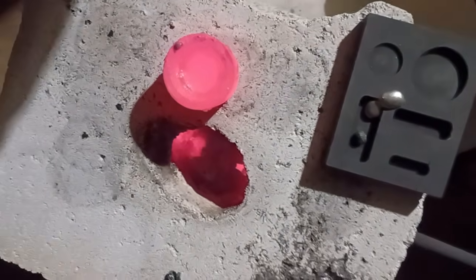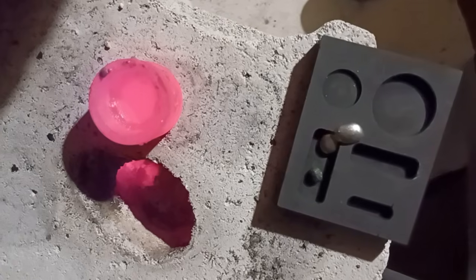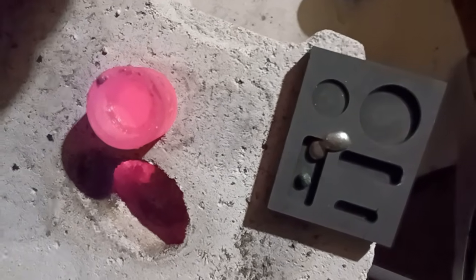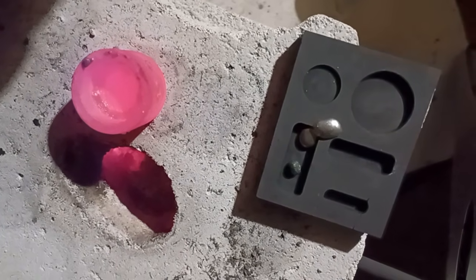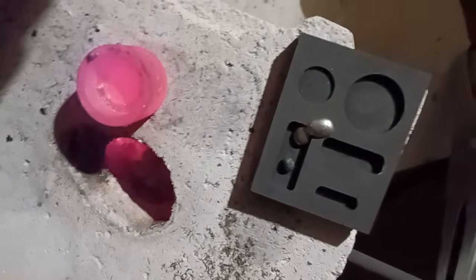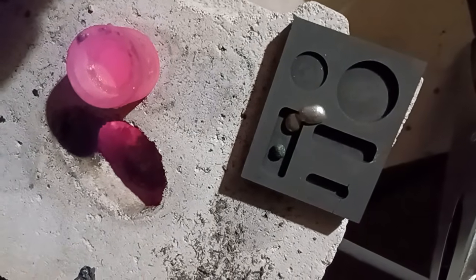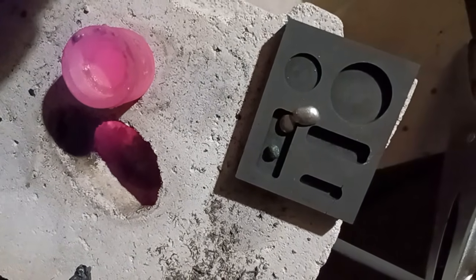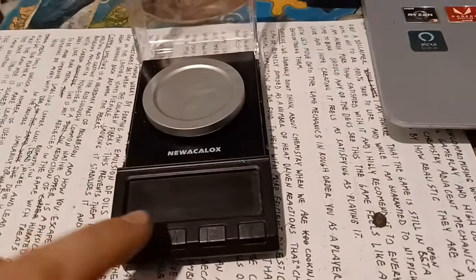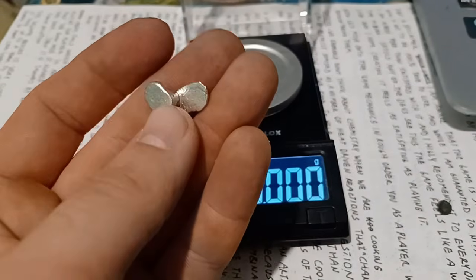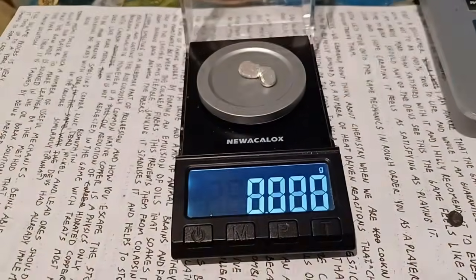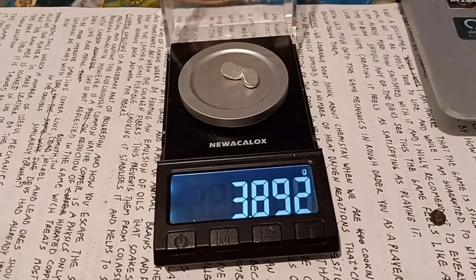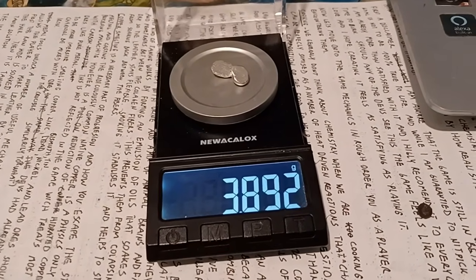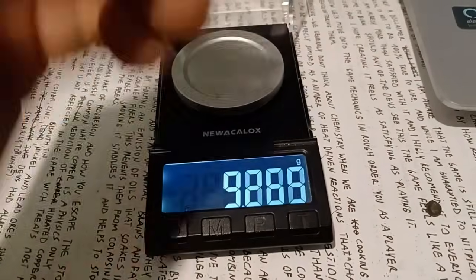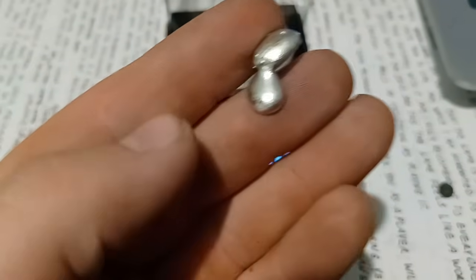The entire melt took 4 minutes. The arc was not on the entire time. I botched the pour and produced some Bigfoot level freehand footage at the same time. I got 3.9 grams of very nice looking silver. I do not know if the weight loss is mostly due to the removal of the impurities or the vaporization of silver, but both no doubt played their part.